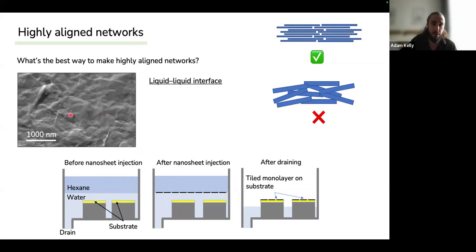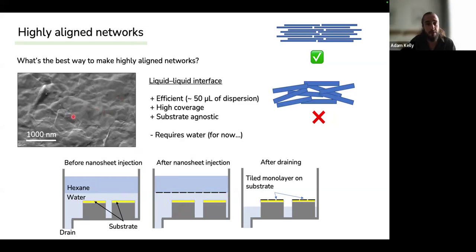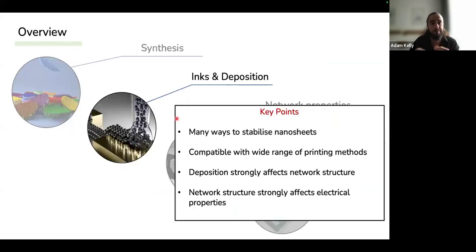And if you look at this network, you get really, really nice conformal junctions out of it. And the benefits are then that you only need a very small amount of material. You get super high coverages of like 95% of your substrate. And you can do this onto basically any substrate as well. The downsides are it requires water, and I have that as a downside because sometimes some 2D materials are reactive with water.